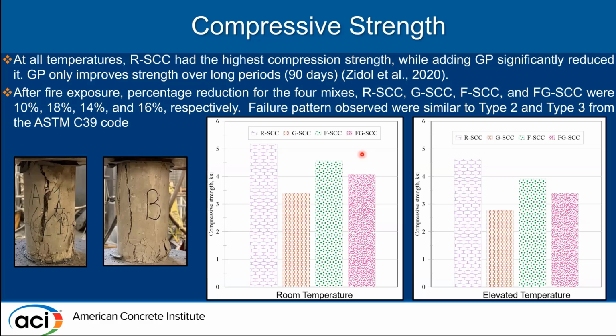G-SCC generally tends to show strength gains over a period of like 90 days. This was reported by Zidol et al. 2020. This is because of the slow pozzolanic chemical reaction that occurs in the glass pozzolan, and any strength before 90 days generally shows negative effects.